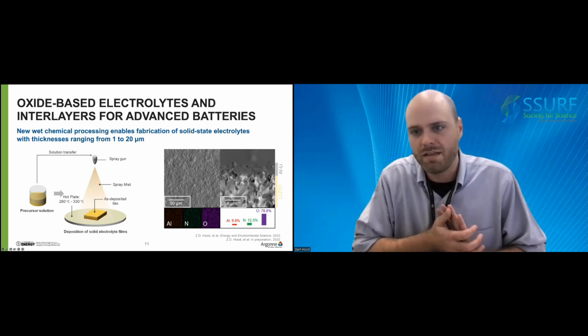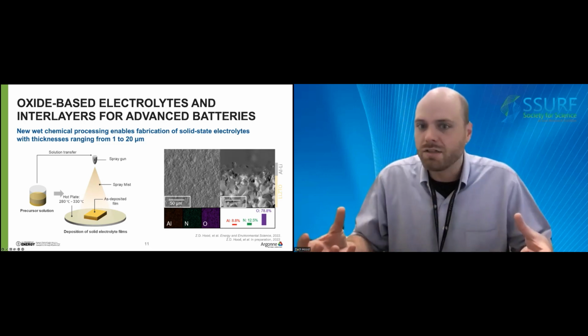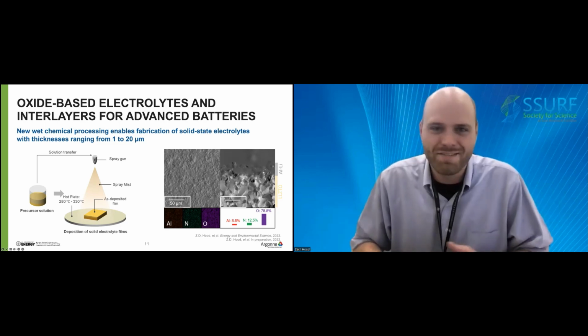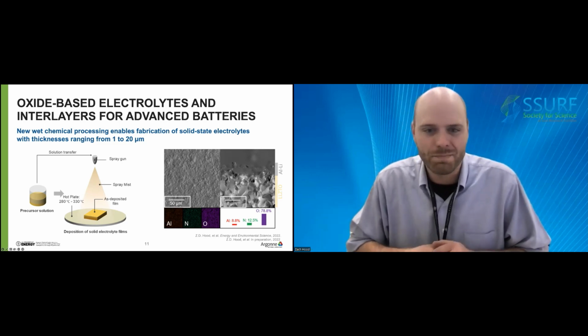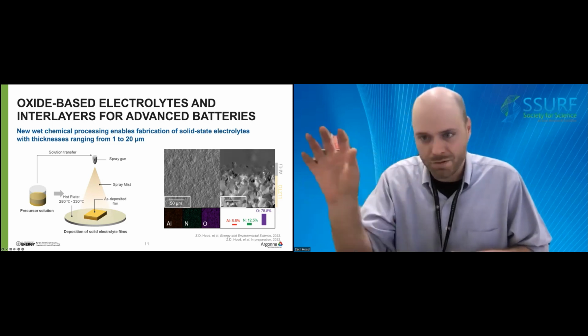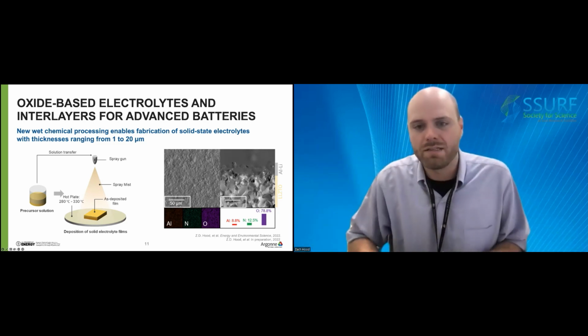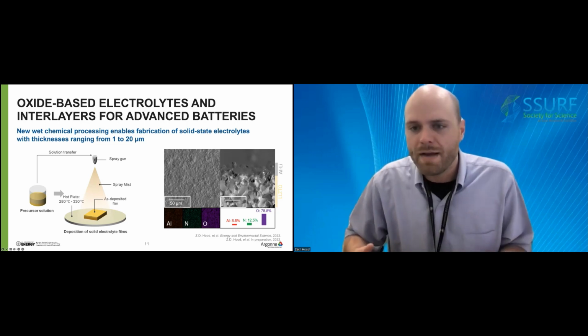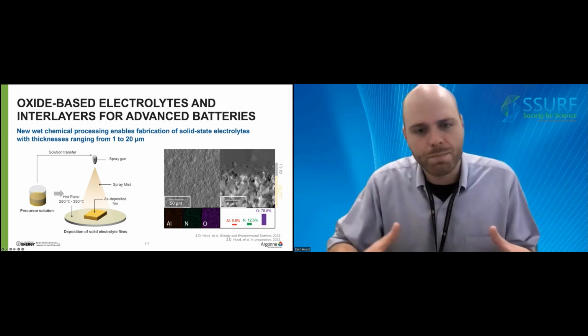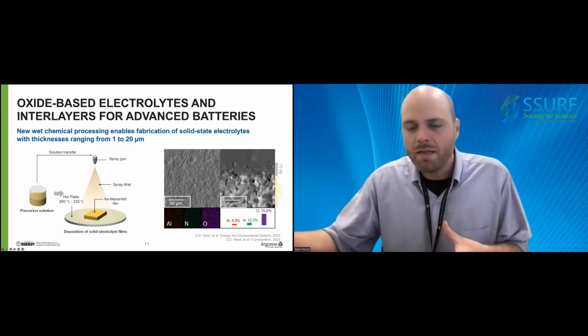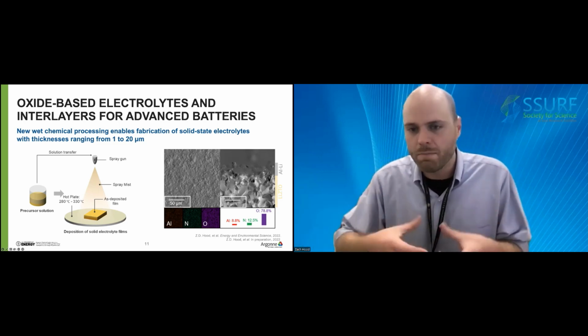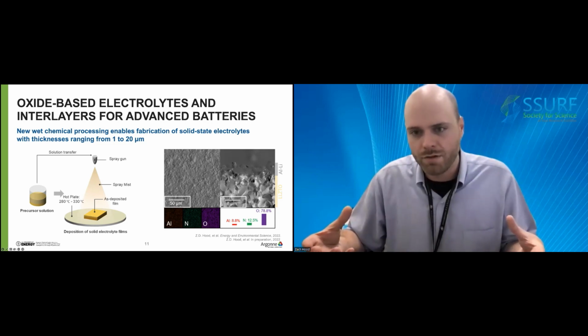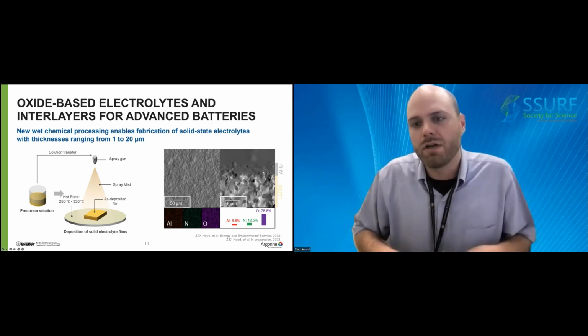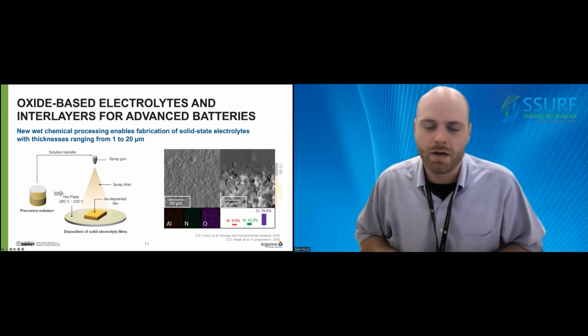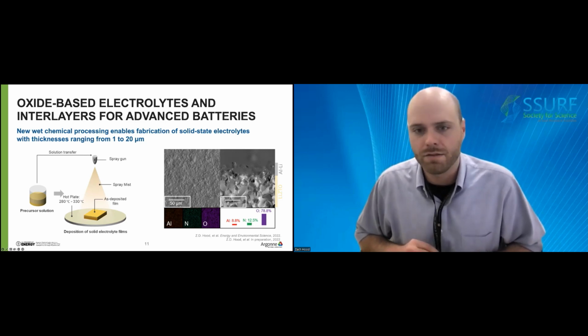a new spray process technique that allows us to manufacture solid-state electrolytes as films that are both thin and slim. The concept is quite simple. We can dissolve our precursors directly into a solvent, spray the solution onto a heated substrate, and grow films of our materials. By adapting not just the deposition temperature, but also the post-processing temperatures, we can make films that have either a polyamorphous type of structure, or we can get fully crystalline films of our materials by adapting some of the processing steps that we integrate into how we fabricate these solid-state electrolytes.